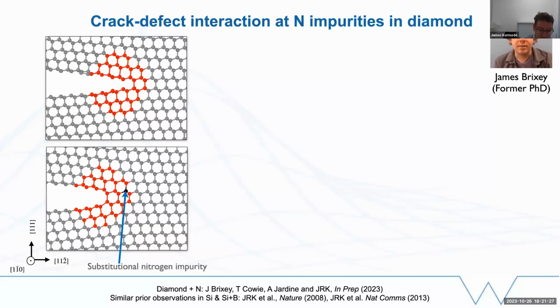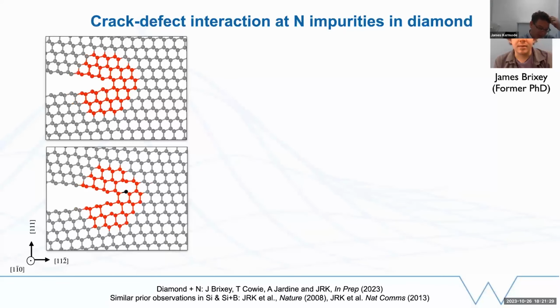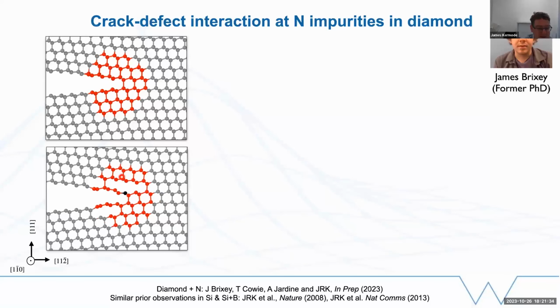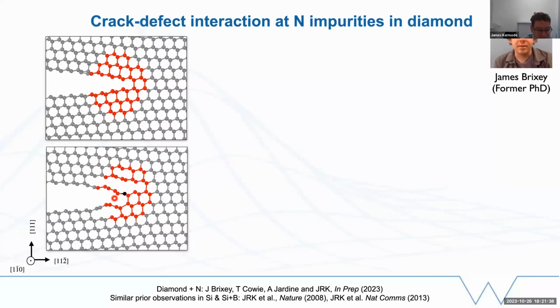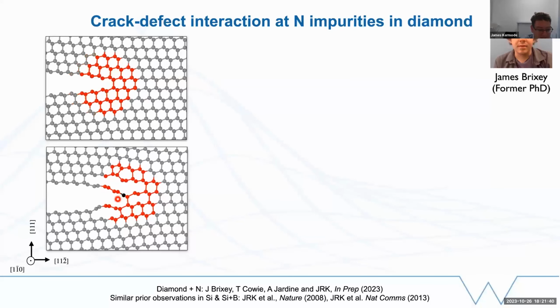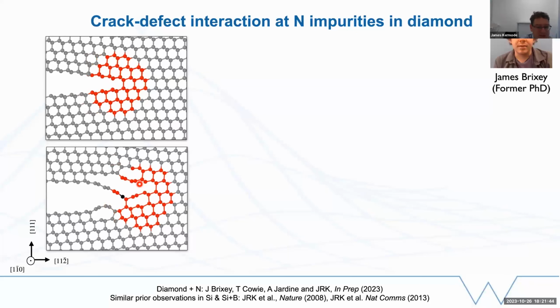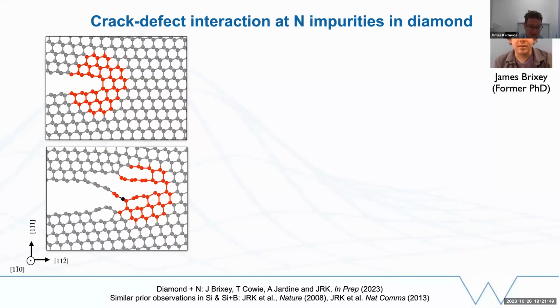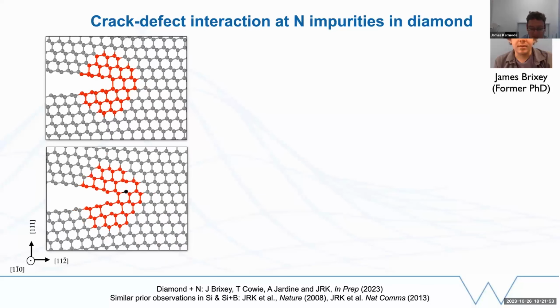If we add a nitrogen impurity, so the black atom here is nitrogen, within a quantum mechanical region, we can add these chemical impurities without any refitting or reparameterization. We now see that the crack interacts with the impurity and stumbles and effectively takes a step up in this direction, in the 1-1-1 direction, by one atomic plane. And that's a nice observation done at the nanoscale, but it actually turns out that it has macroscopically observable consequences.